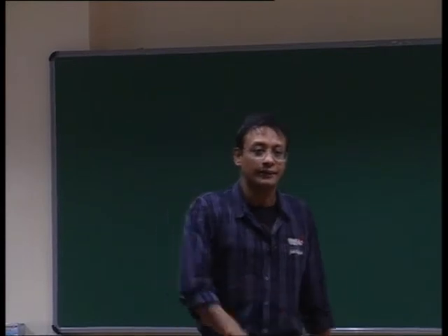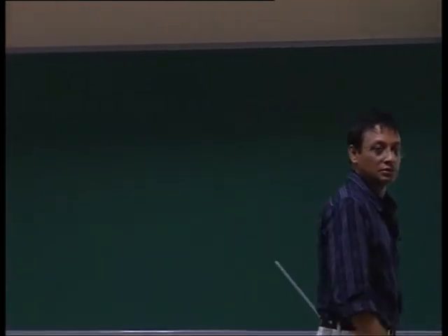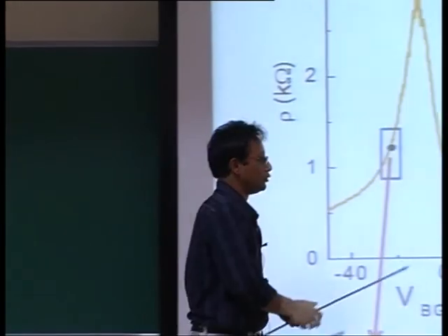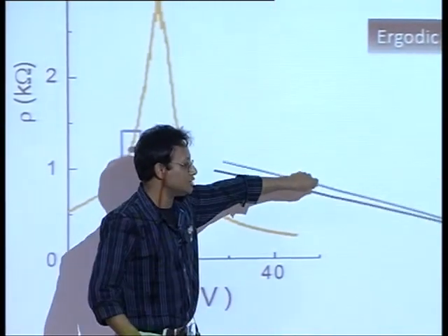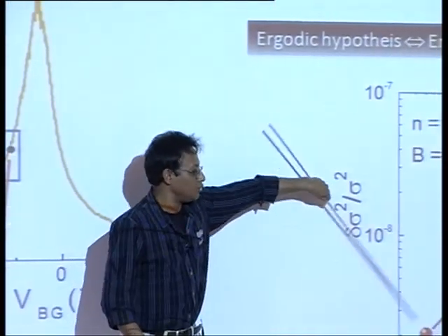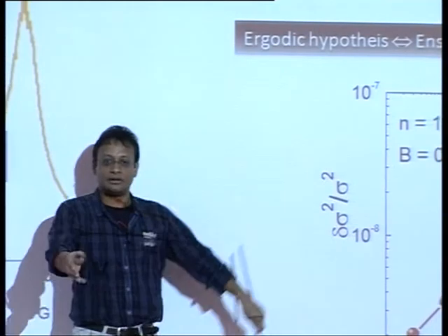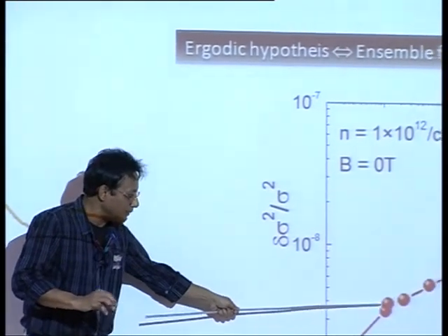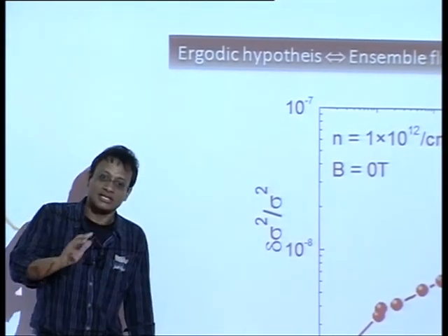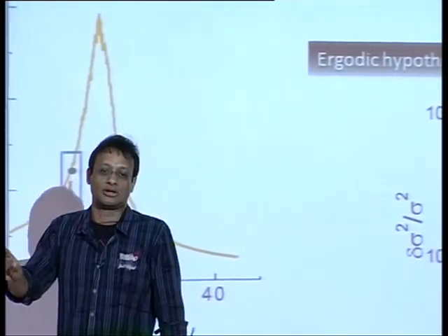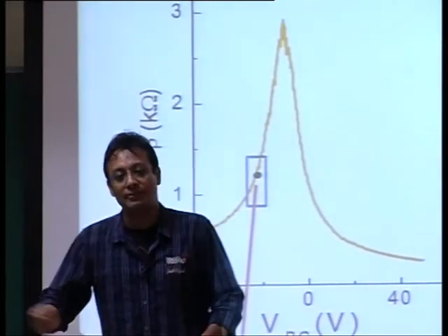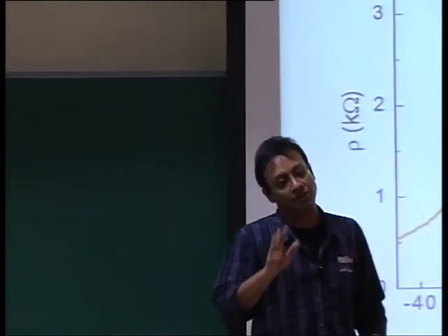Arindam, but does that mean that if you wait for an hour, your point will go up? No. This is variance already normalized. However long you wait, it doesn't matter, because at a particular temperature, noise is determined by how many mobile disorders you have. By waiting a long time, you are not changing the number of mobile disorders. So that remains fixed.